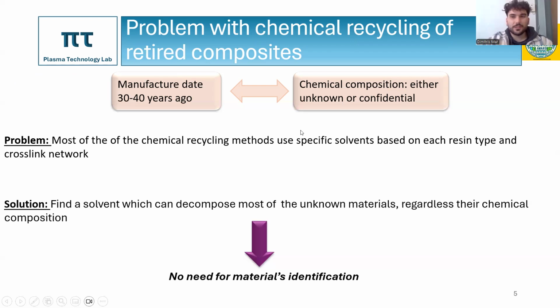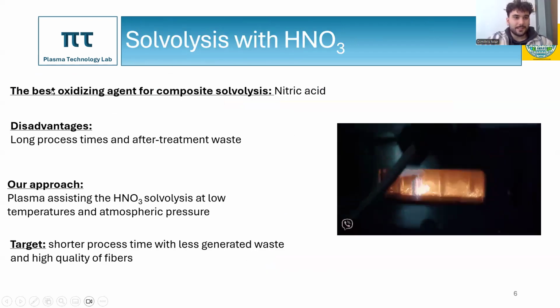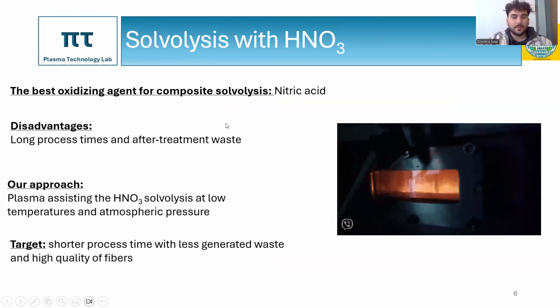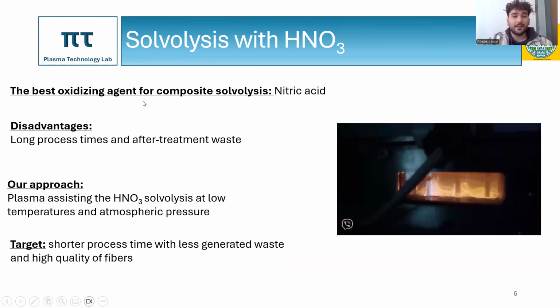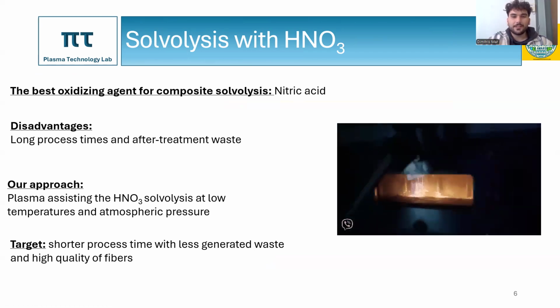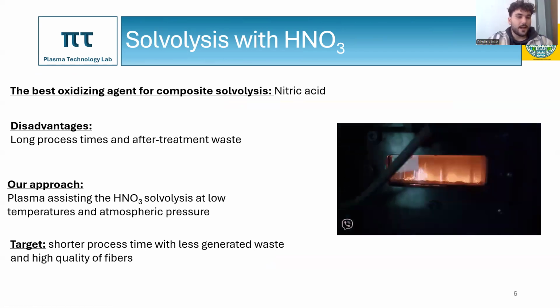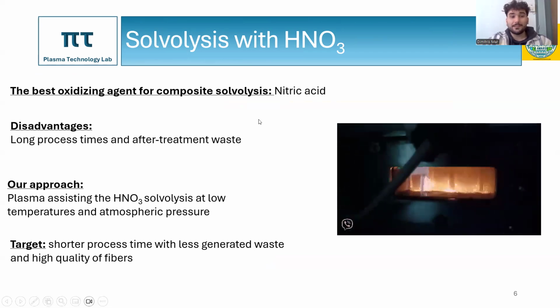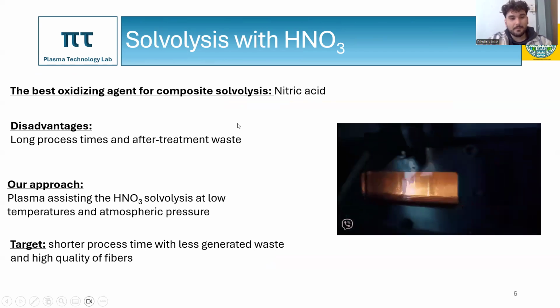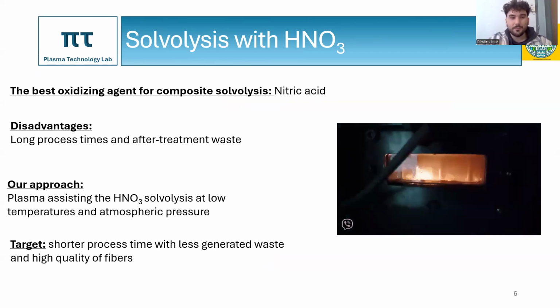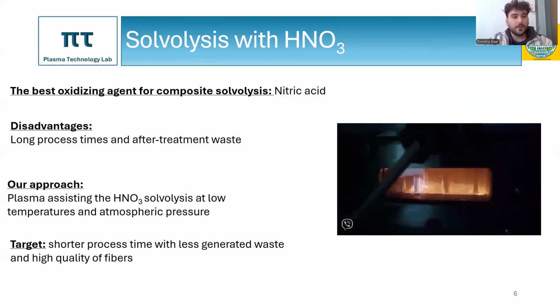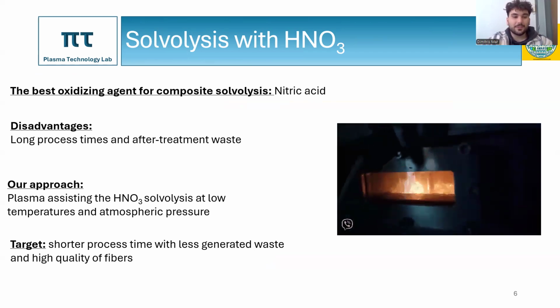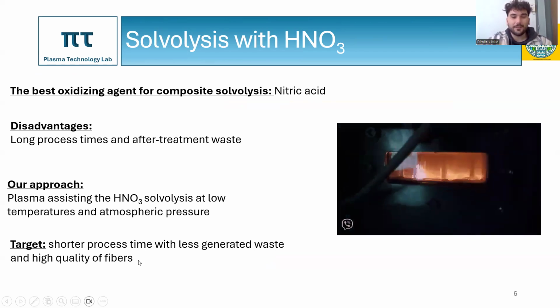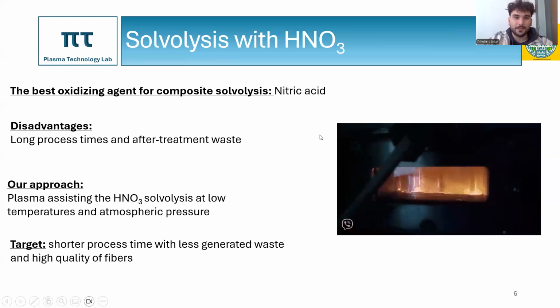That's why we chose a strong acid, nitric acid, because it is the best oxidizing agent for composite solvolysis, but its disadvantages are the long process times and the after-treatment waste. Our approach to deal with those disadvantages is by plasma assisting the solvolysis, aiming for low temperatures and atmospheric pressure. Overall, our target was to achieve shorter process times with less generated waste and high quality of fibers.